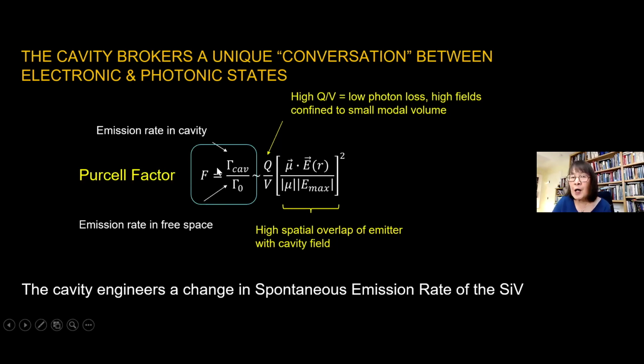And our hope is by instituting this unique environment that we can actually make this Purcell factor quite a bit larger than 1. And what that means is that somehow we're brokering a conversation, an exchange, an almost lossless exchange of energy between electronic states in the silicon vacancy and photon states in the cavity, so that the emission rate in the cavity is maybe orders of magnitude higher than it would be normally. These components tell us what is important in doing this. And it's a different way of describing what I said initially.